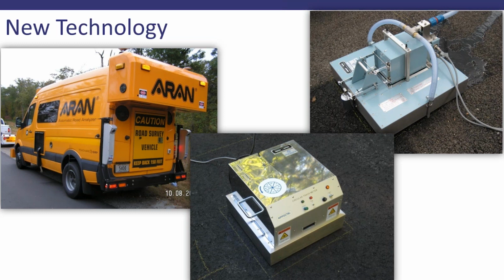The picture in the bottom middle is the circular track meter. This is more of a laser texture meter. So that sand patch test that I showed you, this is a fancier way to do that. So it uses a laser that moves around in a circle underneath that silver box, and it actually measures the amount of texture for that track or for that circular area. And then at the top right is a dynamic friction tester, and this is one that's got a motor, so it basically spins that rubber foot. This would be the comparison to that British pendulum that I showed you a couple of slides ago, but it gets the speed up to 80 kilometers per hour in a little circle under there.